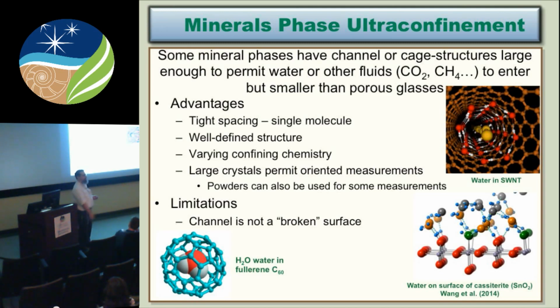If you want to consider this with respect to a grain surface, the surface of a beryl is not a broken surface. There's no charge that isn't compensated by something else in the mineral. So you don't have these open oxygens that want to grab hydrogens, for instance, that you normally see on, say, a broken quartz surface.